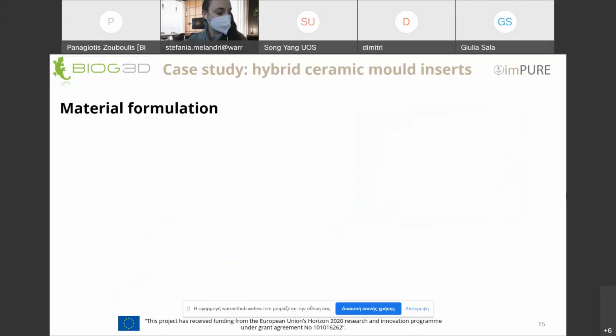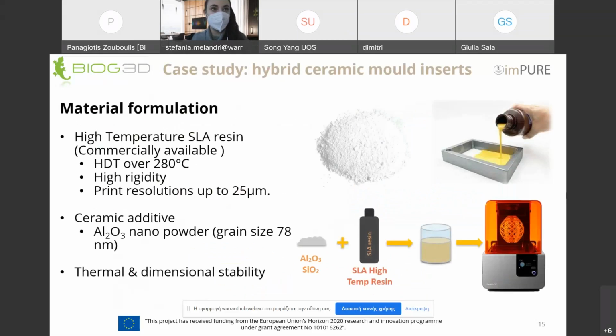And let's talk about the material for a minute. We use high temperature stereolithography resin. Stereolithography is a VAT photopolymerization process that uses a laser point to solidify the material. It has a heat deflection temperature over 280 degrees. That means that it is a material that is suitable to operate up to that temperature, a very rigid and hard material that can be printed with high printing resolutions up to 25 micrometers. We have added a ceramic additive, aluminum oxide nanopowder, that helps preserve and enhance the thermal and dimensional stability of the printed components.